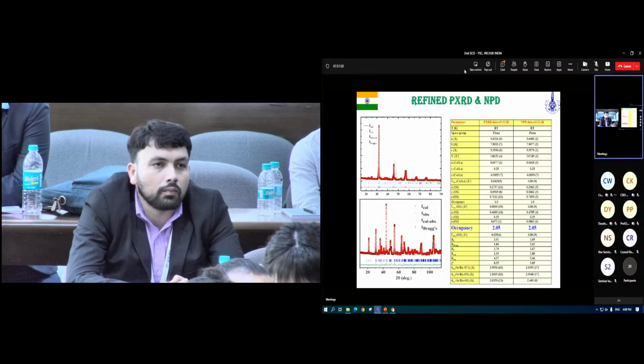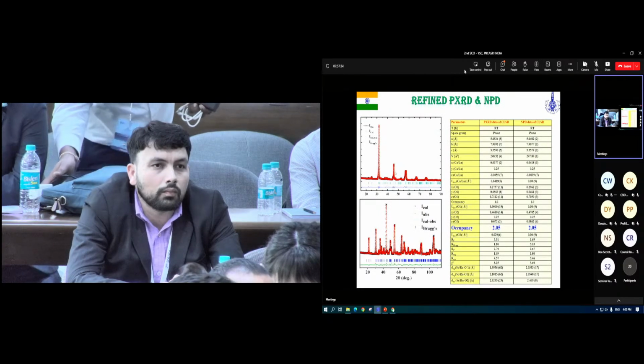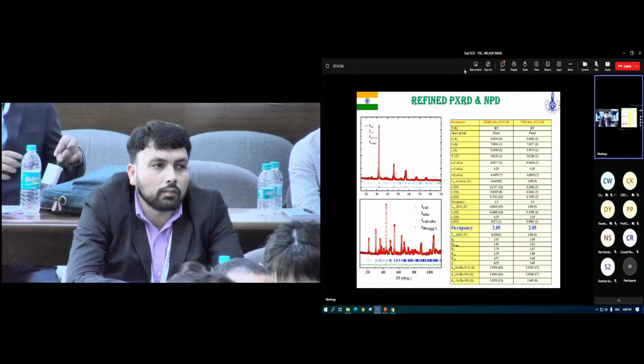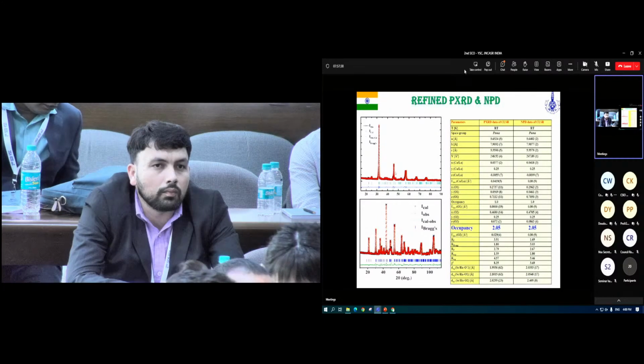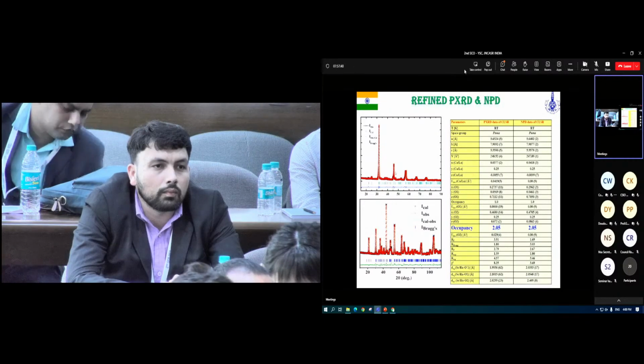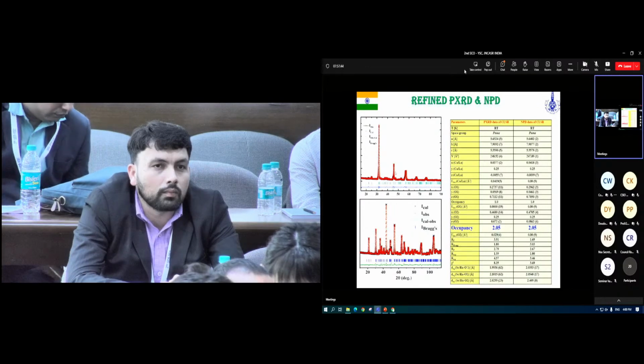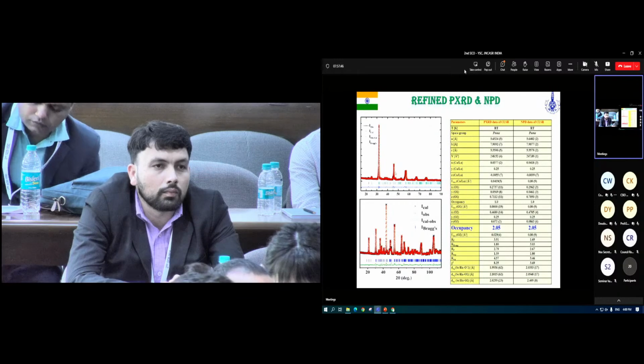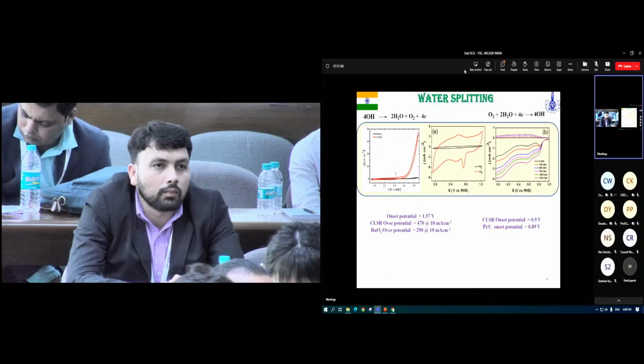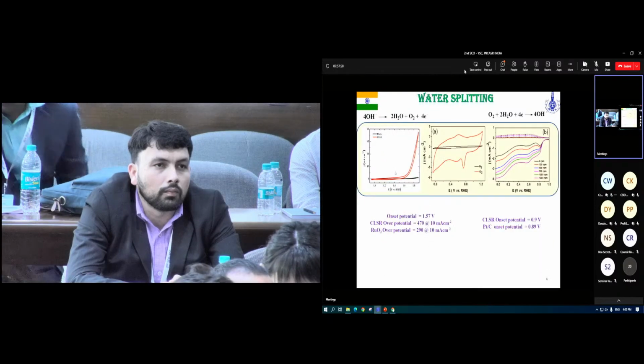After synthesis of these materials, we collected XRD and neutron powder diffraction data, refined those data, and found that this is a pure single phase. This is the Rietveld refinement data, and we can see clearly that all the peaks have their Bragg peaks, and all the parameters are in a very good range. After all the characterizations, we use these materials for water splitting reactions.